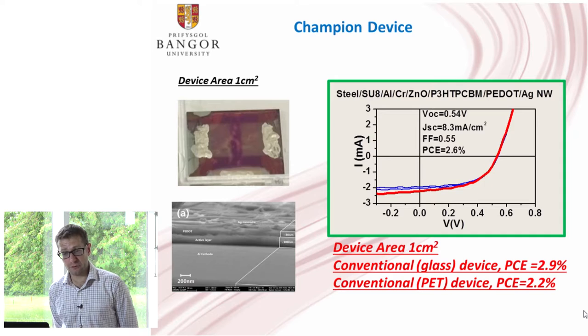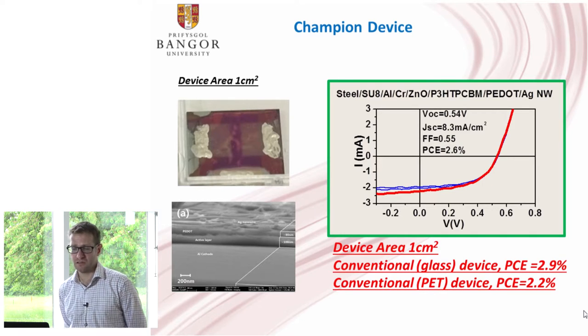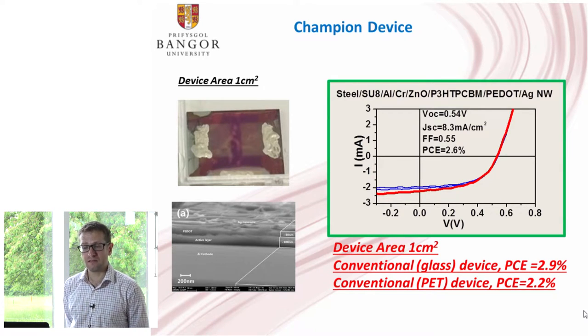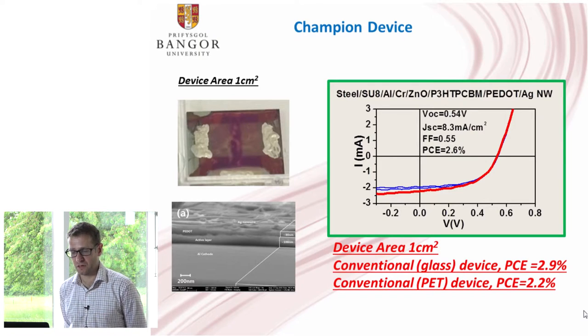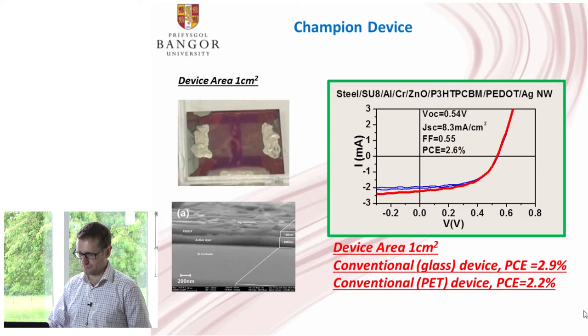In terms of the performance we get from this configuration, it's around 2.6% efficiency, over a relatively large active area of around 1 square centimeter. It's slightly lower than the performance we get on glass substrates, where we get around 3%, but slightly higher than on a PET substrate, which is around 2%.